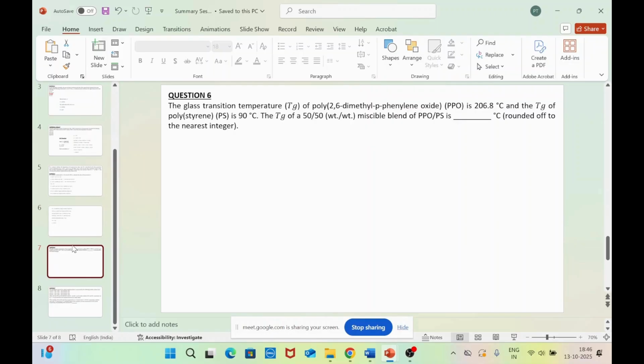I think this is a very simple one, so this should not be of much difficulty. But again, if you have any doubts related to the last questions, please let me know. Till that time, let me read out this question. The glass transition temperature of poly 2,6 dimethyl paraphenyl oxide, PPO, is 206.8 degrees Celsius and the glass transition temperature of polystyrene is 90 degrees Celsius. What will be the Tg, that is the glass transition temperature, of a 50-50 weight percentage miscible blend of PPO and PS? So calculate that value of Tg.